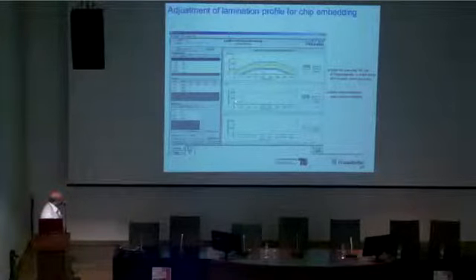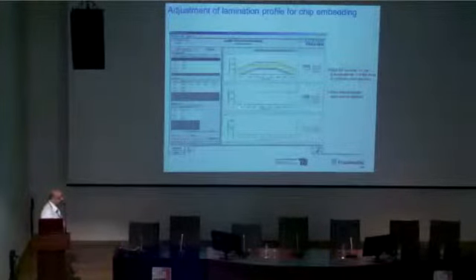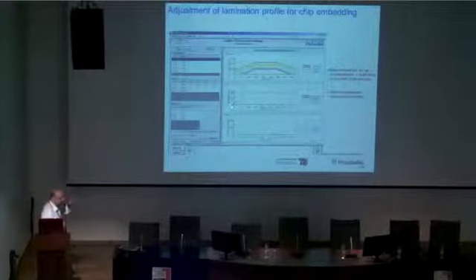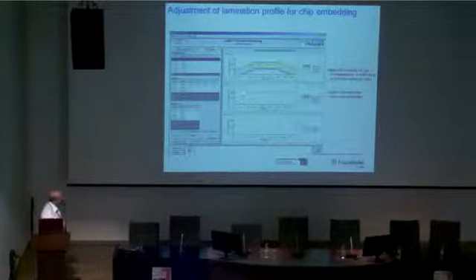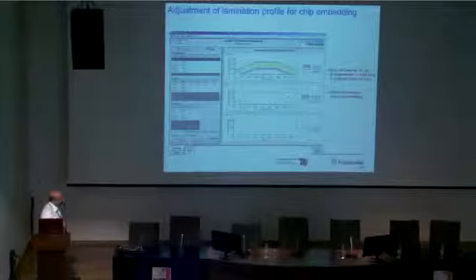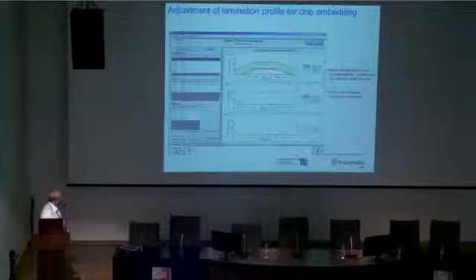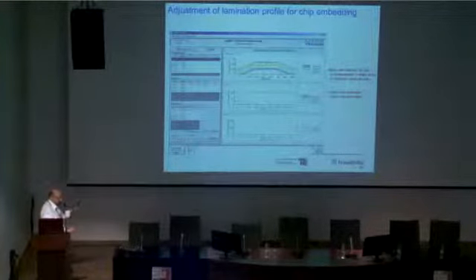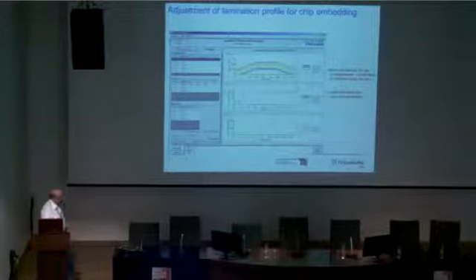In the meantime, you apply very carefully a pressure of 5 bar in the beginning, and only when you have reached a temperature of about 80 to 100 degrees and the viscosity has stabilized, you increase the pressure from 5 bar to 20 bar. You keep the pressure constant during the curing profile. Also, needless to say, the whole process takes place in vacuum. So you apply vacuum from the beginning.